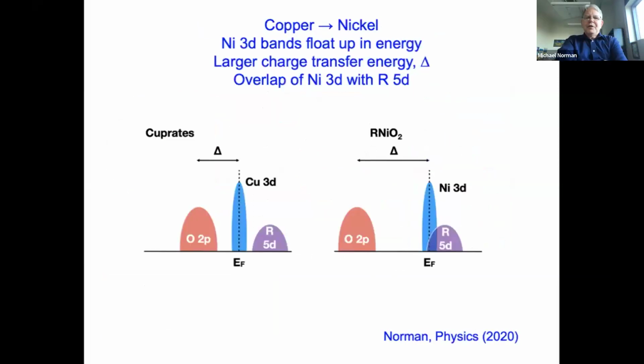And so the way to think about this, of course, is that the nickel is 1 plus. It also has an ionic charge 1 less. And so the net result is, relative to copper, the nickel 3d bands float up in energy. And so this not only increases the charge transfer energy between the nickel and oxygens, it also leaves an overlap of the nickel 3d bands with the rare earth 5d bands. And this is a difference from cuprates.